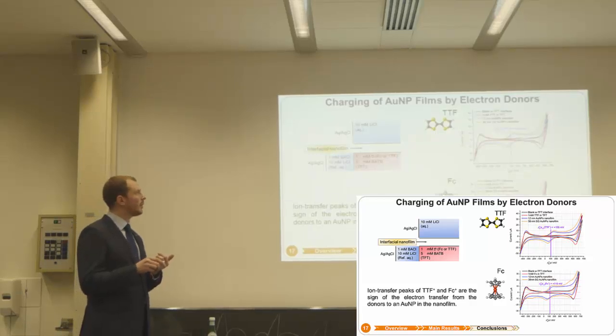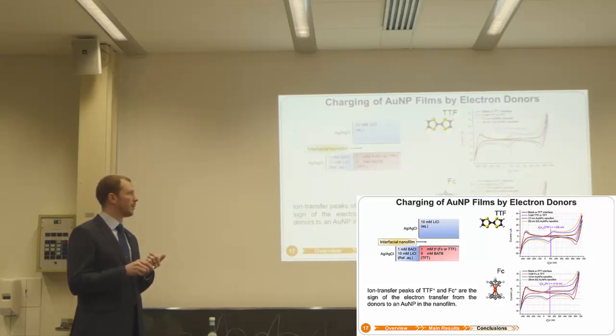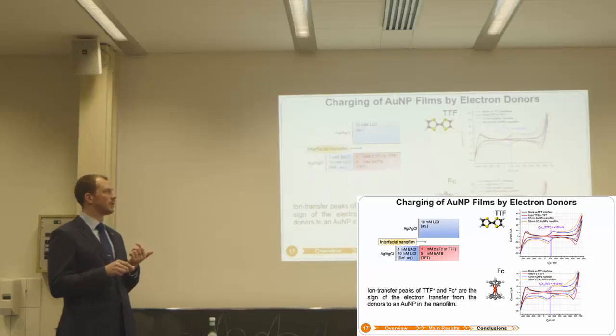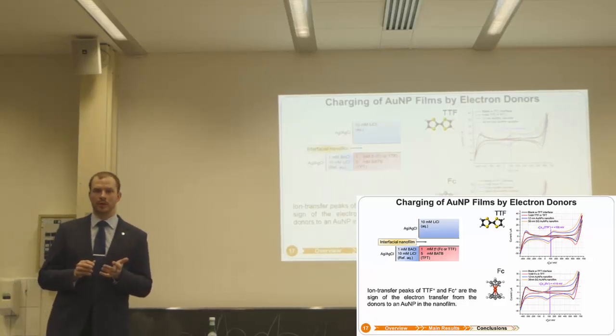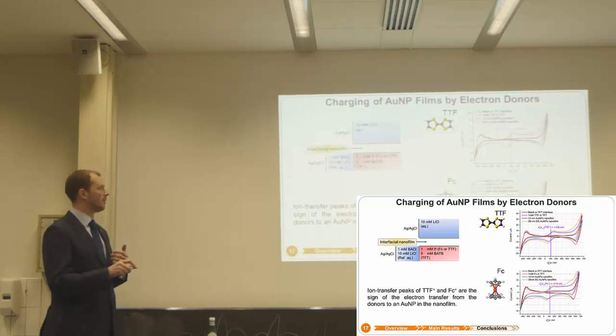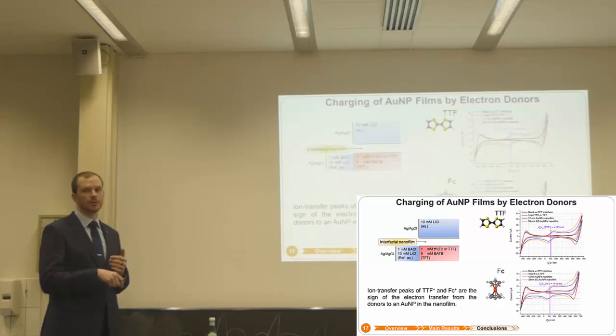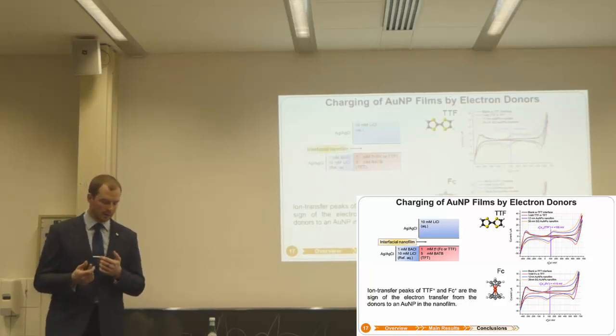And just to prove that it's not an artifact or some special interaction between nanoparticles and TTF, we did the same with a completely different electron donor molecule, ferrocene, which has more or less the same redox potential. And we observed similar effects, an increase of current in this region that corresponds to transfer of the ferrocenium ion.